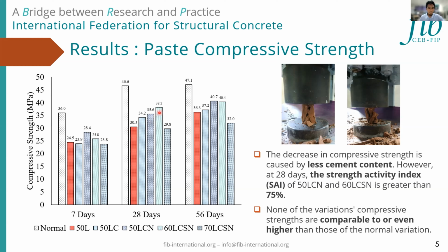We can see that variations such as 50 LCN and 60 LCSN have a strength activity index of more than 75%. And it should be noted that none of the variations of the variations' compressive strengths are comparable to or even higher than those of the normal variation.